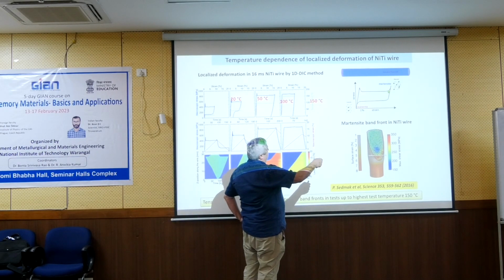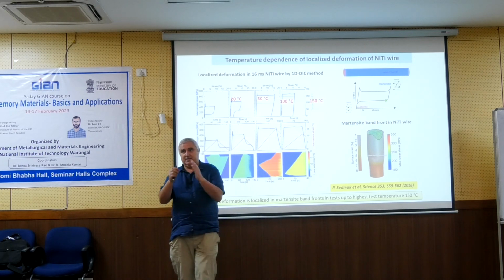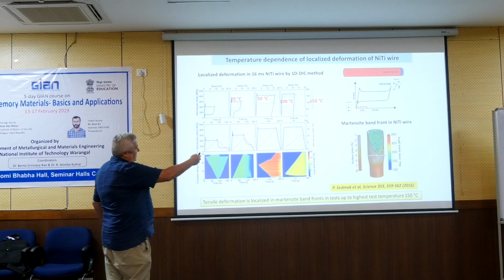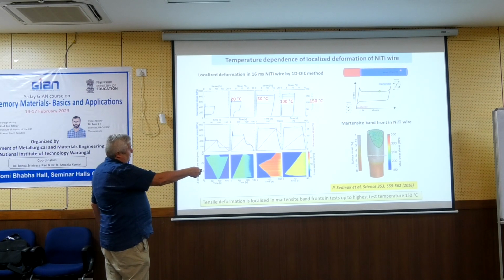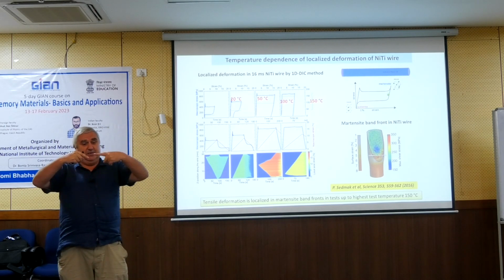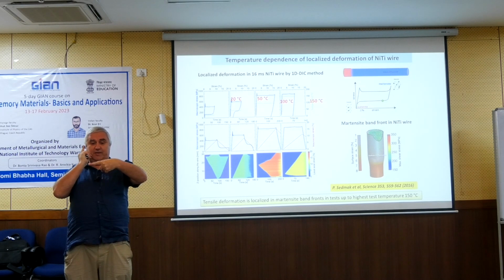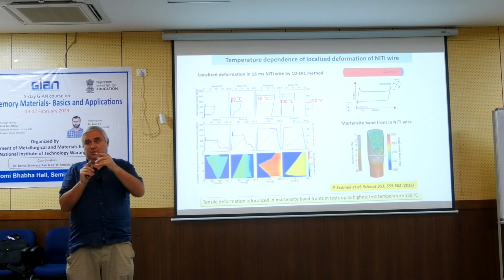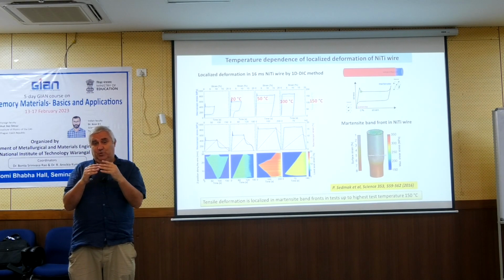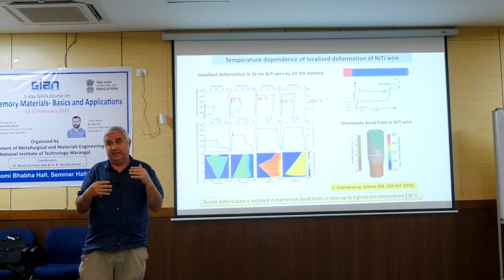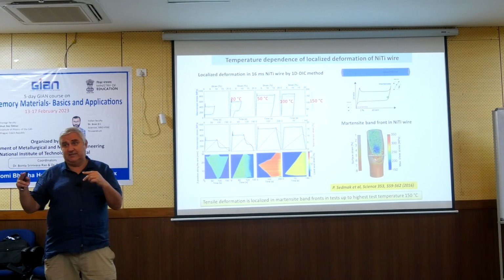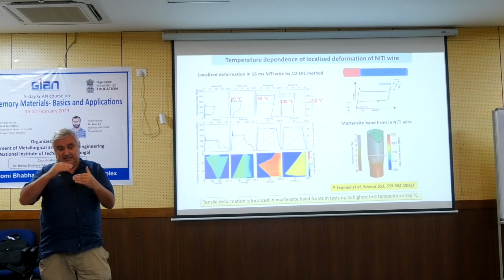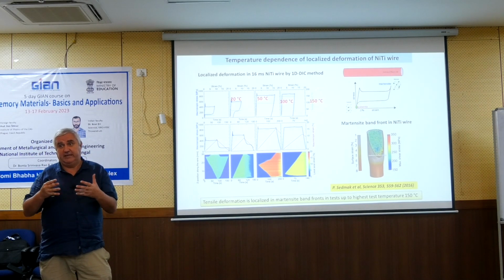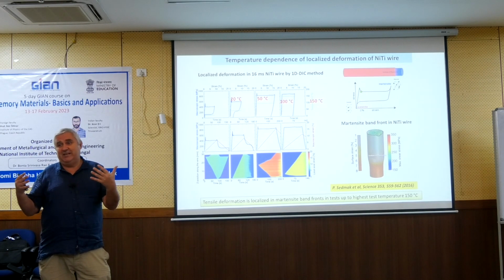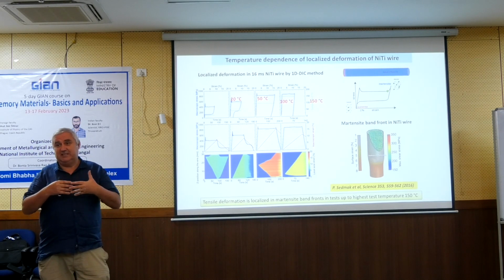You have here this peak. So you are loading, and then there is a drop. Why is this here? Because now the band is formed. There is a jump. In reality, if you look at the surface, it could happen in the middle of the wire, and suddenly you have a thin band which appears in the middle. So there is a nucleation which is necessary for that. You need some overstressing, or if you do cooling and heating, you need undercooling to nucleate the band. Once you nucleate the band, it propagates at constant stress. So you are perfectly right that the hysteresis is connected with undercooling and overheating, but it is not the physical origin of it. It only somehow modifies it. The physical origin is the dissipation of the energy.